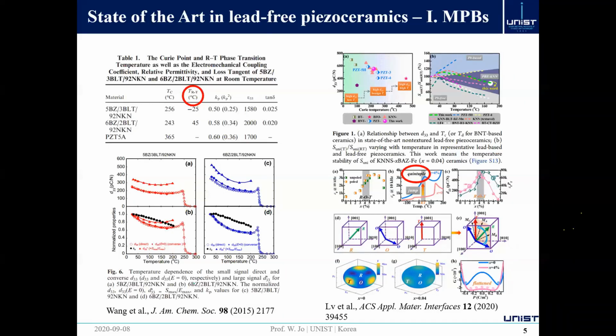Here, one of the noteworthy achievements is given by Jia Gang at Sichuan University. It seems that these days he's the only one who's breaking the record again and again. At the moment, officially or unofficially, the piezoelectric coefficient he achieved was somewhere around 600 picocoulomb per Newton, which is a really, really high value.